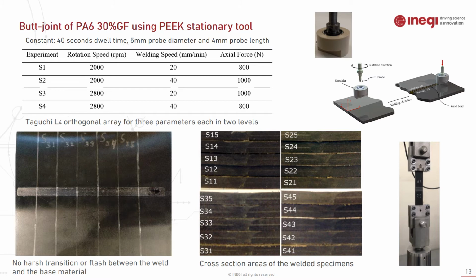A Taguchi table was conducted for the optimization process for 3 parameters, each in 2 levels: rotational speed, welding speed, and axial force. 5 specimens were produced for each combination and tested to study the effect of the welding parameters on the joint strengths.